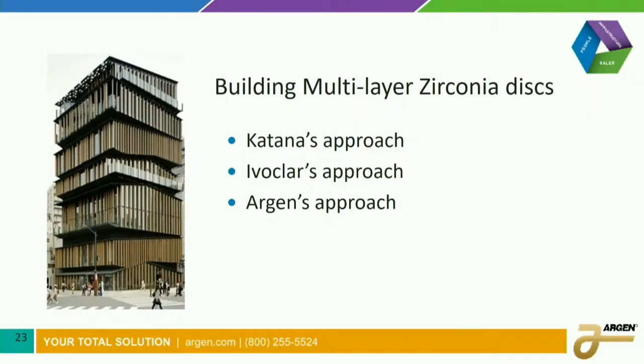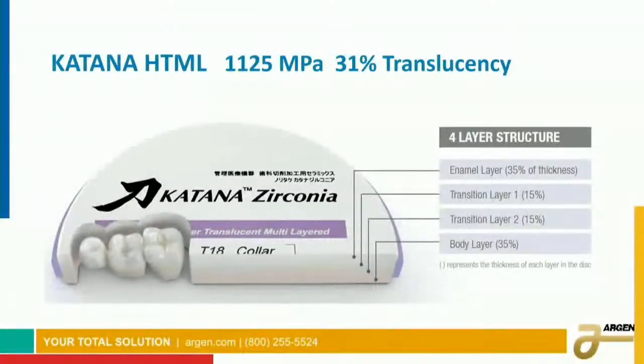Okay, now we're going to talk about 3 different companies' approaches to building multi-layer zirconia. Katana, as you know, was the first company to introduce multi-layer zirconia, and they decided on a 4-layer structure. Independent of the size of the disc, they keep the enamel layer at 35%, and then 2 transition layers, and then finally a body or a gingival layer, again at 35%. So they keep these percentages independent of the size of the disc, which sometimes results in not enough coloration in the middle third of the restoration. Okay.